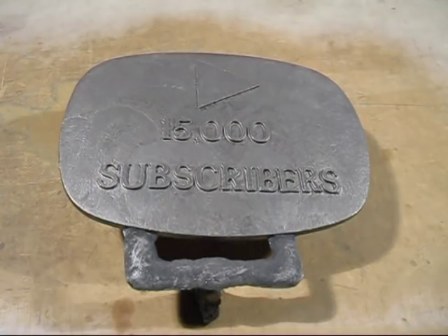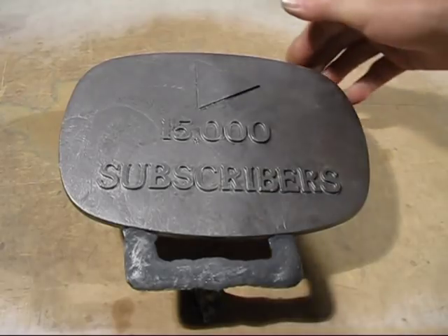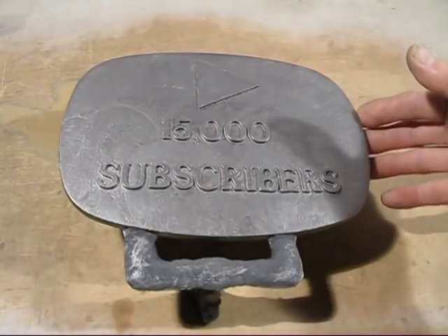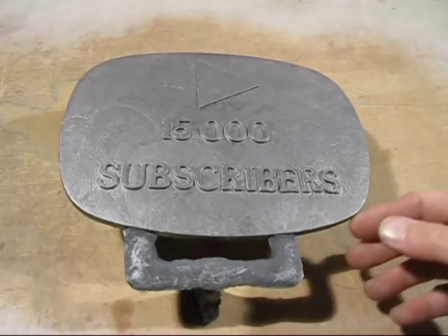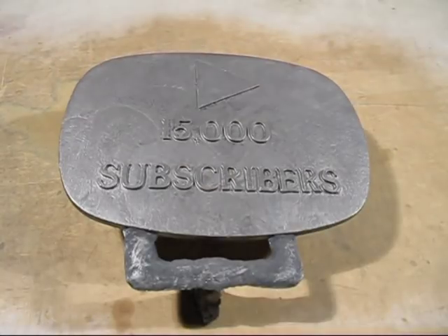One of the problems with having too fine a sand and also maybe too much oil, you would think that the mould will not fill up without vents, but there is no vents whatsoever on the mould. So have a look at the casting here, there's no vents and it's still filled up. Most of the time if your mould does not fill up, it's usually because the metal is not hot enough.